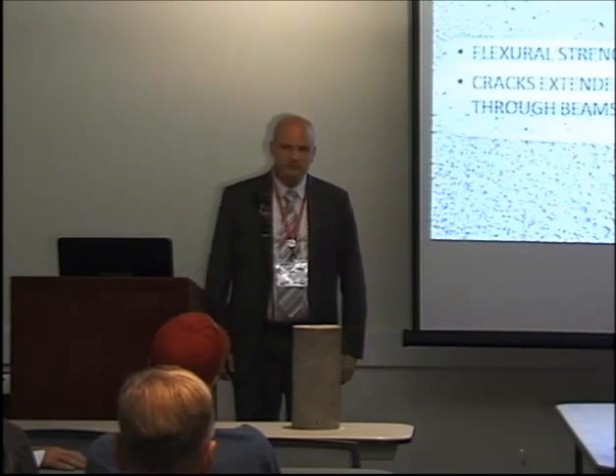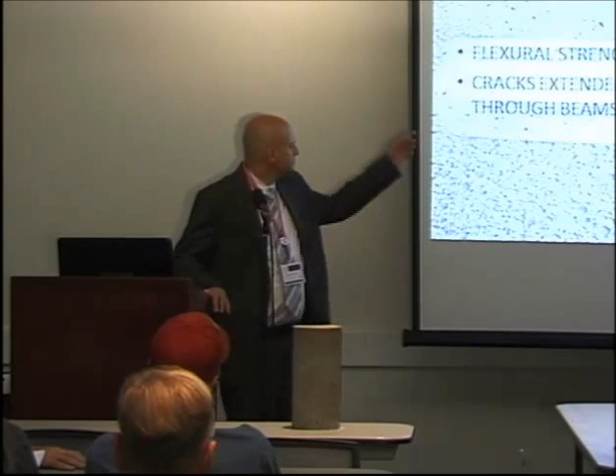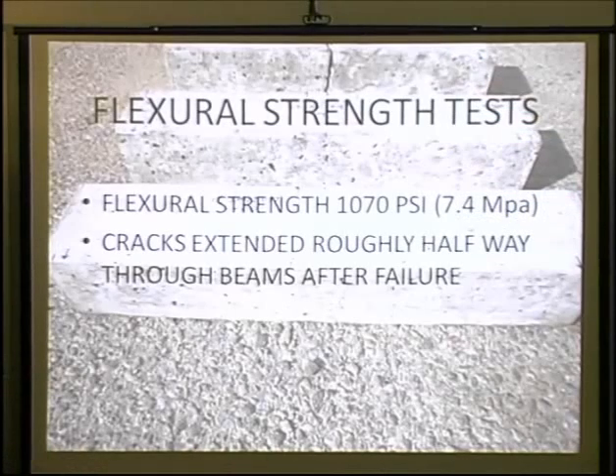And I did flexural strength testing on these beams here and got good flexural strength, 1,070 pounds per square inch. The way that works is to support the beams at the end, apply a load in the center till it breaks. Interesting thing about this cement is that while with Portland cement concrete, once it starts to crack, that crack propagates all the way through and it fails completely. With this, the beams didn't fail completely.